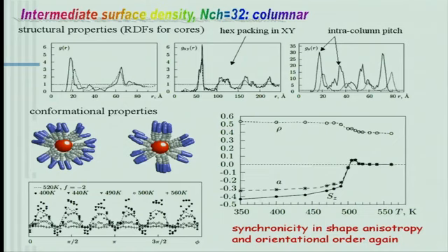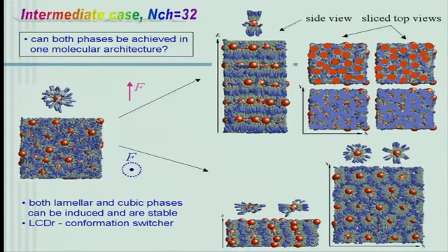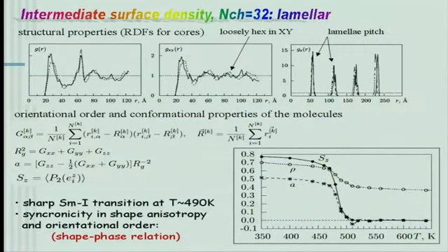And this is another question. So both phases disappear at the same transition temperature of about 490, 500 degrees. So that means that these locks provided by symmetric ordering are responsible for destruction of this phase. Since here the liquid crystalline subsystem is having the order-disorder transition, after this the system splits and there is no ordered phase.